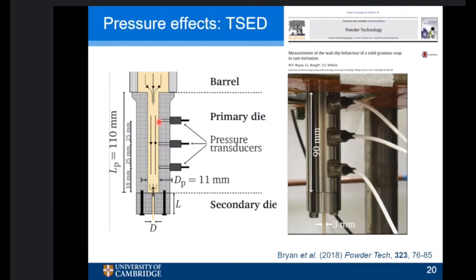Okay, I'll start with the first one. The thermal conductivity of the material, well, obviously it depends on the nature of your particles. Tungsten carbide is pretty dense, so it has a very high thermal conductivity, whereas more food materials tend to be around that of water or smaller. So it's very much related to the nature of the material, but also whether or not there's any orientation of the particles as a result of the flow.